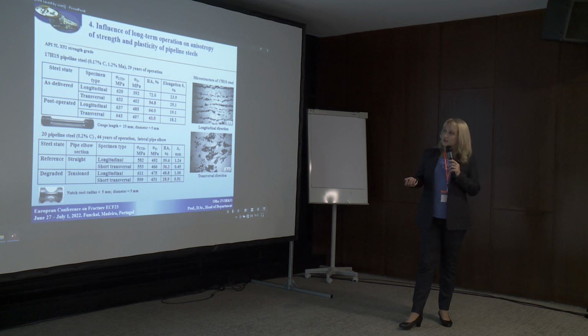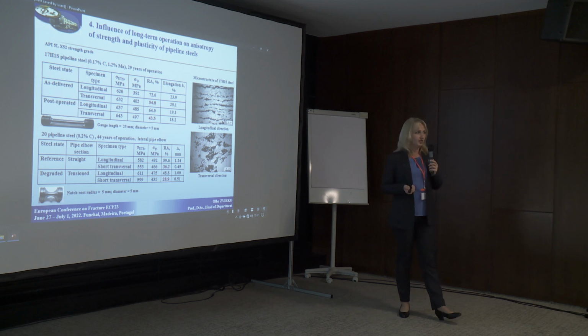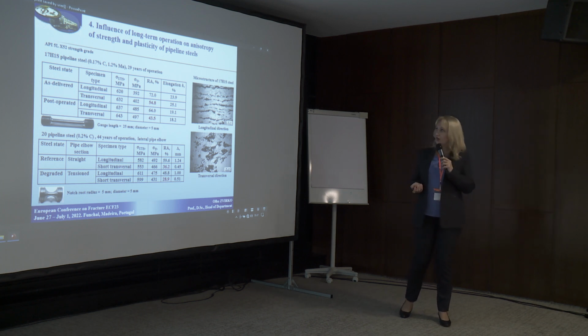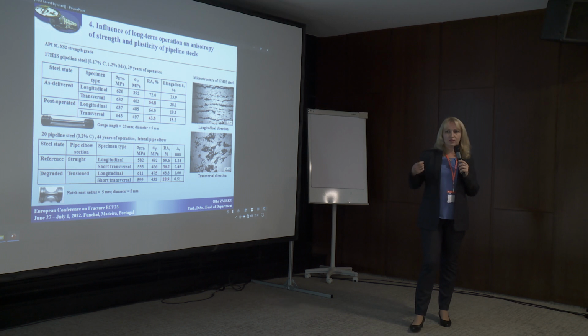So as can be seen, the anisotropy in strength properties is insignificant for both studied steels. However, it's pronounced in the plasticity characteristic, reduction in area. And also long-term operation influences anisotropy. For example, for the low alloy steel, anisotropy in reduction in area was about 20% higher for the degraded steel compared with the as-received one.